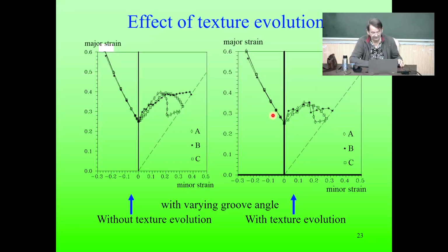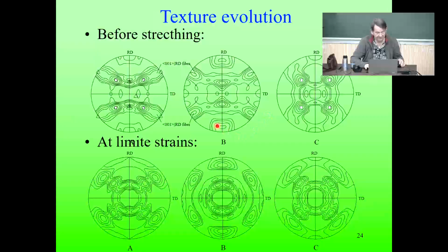And then also for the negative part. Tensile testing is somewhere here. But this tensile testing is actually a line here. It's not plotted, but more or less this line. So there is evolution in the texture, you see. So this texture goes into this one, into this one, and so significant changes are happening in the textures.